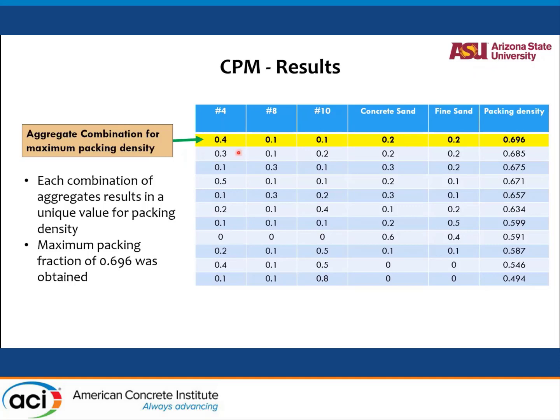These are all the packing values arranged in a descending order. So the one that has a maximum is up in the top. So this combination of aggregates that you see here, 40% of number 4s, 10% number 8s, 10% of number 10s, and 40% of sand total gave us the highest packing density. Again, this can be changed once you have the individual dry rodded unit weights of the set of aggregates that you're going to use for UHPC.